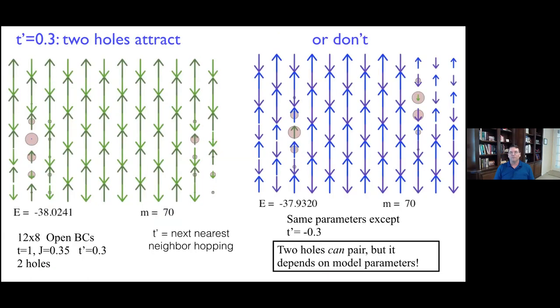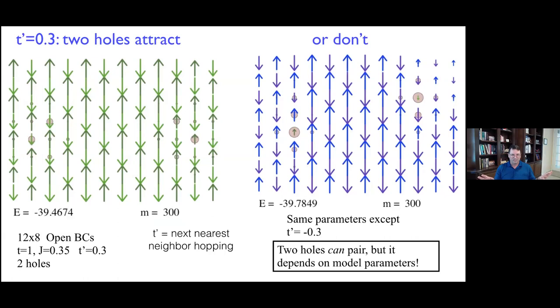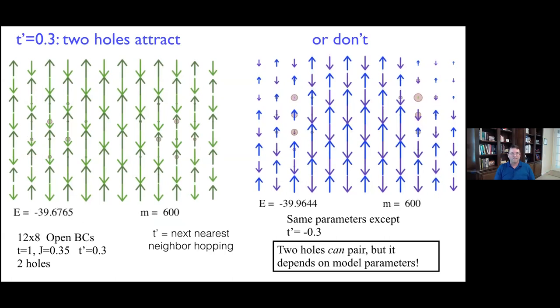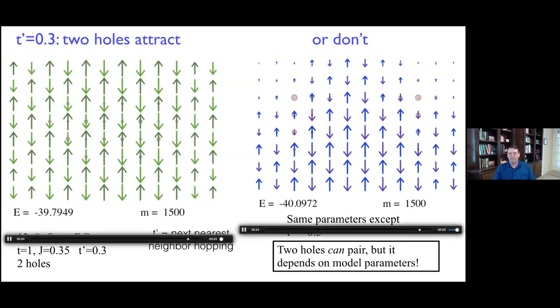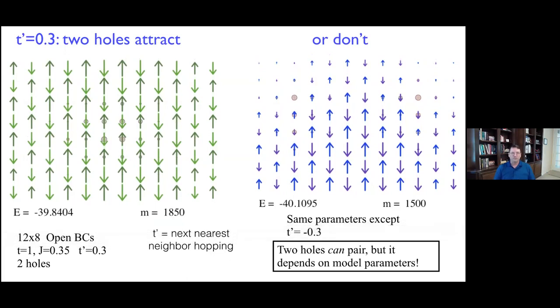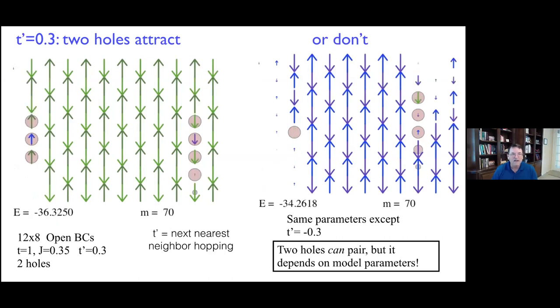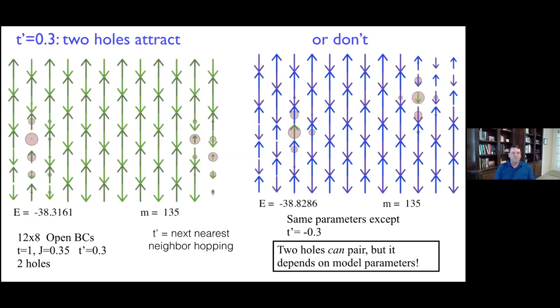Here are two movies going simultaneously that show two different parameters. Each of these starts essentially in a product state, and there are two holes doped, one on the left side of the system and one on the right side. The two different cases are t prime equals 0.3 and t prime equals minus 0.3 on the two sides. I'll start this again. The two holes started apart, and as the DMRG evolved, we see the energy decreasing and the number of states kept increasing. And what happens is, in the model with t prime positive on the left, the two holes see each other and they bind together.